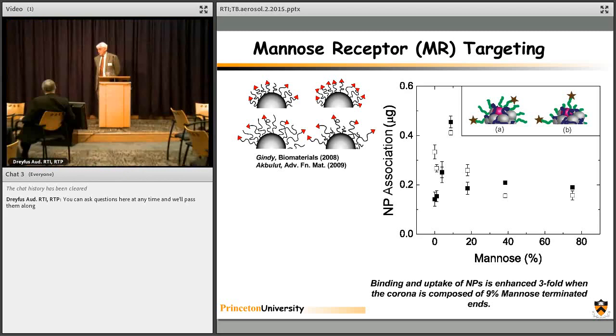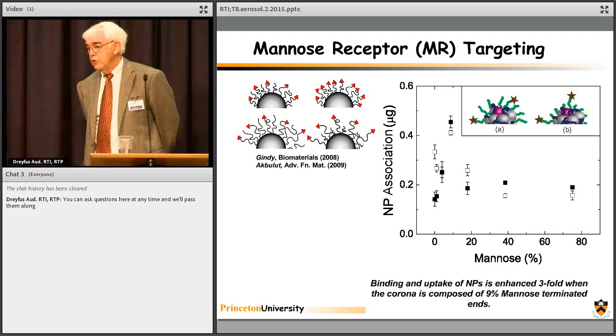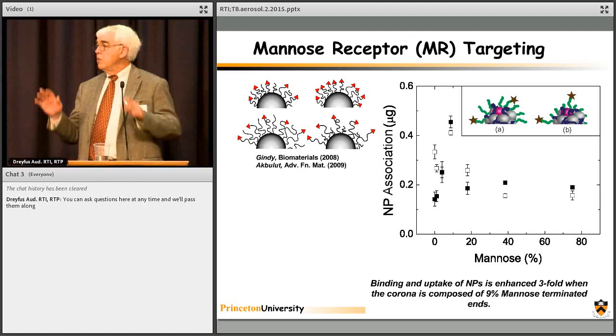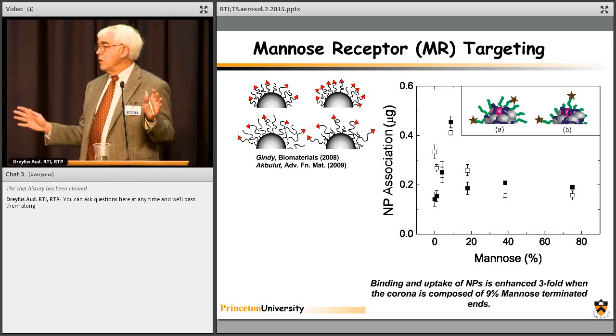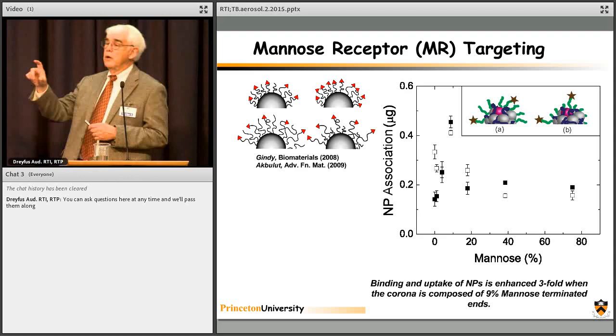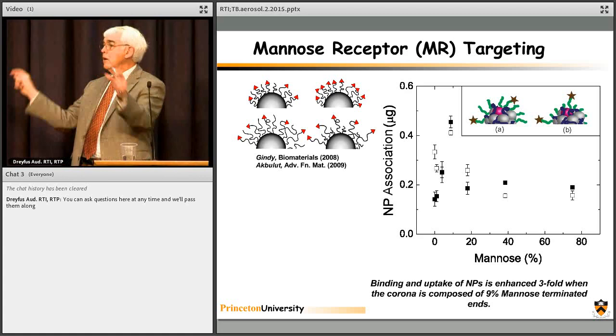which we haven't looked at, either lower, I'll tell you why, and we haven't looked at the drug, the PEG effectiveness in circulation that is protecting it. If you went too low in PEG, I think you would get the problem, like we showed with the peptides, that it may not be a uniform coverage. But I didn't mean PEG, I meant the styrene. I'm sorry. The styrene. Yeah. If the styrene is too small, you may not get sufficient anchoring energy, so you may get patchiness or uneven distribution. Okay.